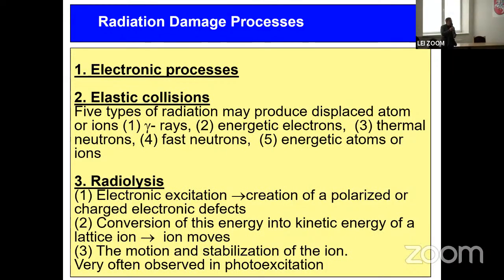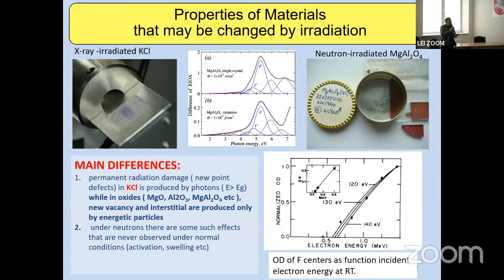Because in this case, defects will be created even by UV radiation, but it's not the case for materials important for fusion. So this slide just shows you that, for example, in order to create defects in spinel crystals, which are from the priority list of the International Consortium, we need electrons with energy higher than 500 kilo electron volt to create new vacancies, and these new vacancies could be detected by measurements of optical absorption shown here.